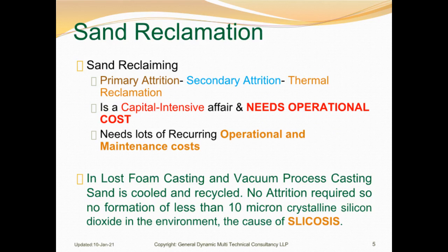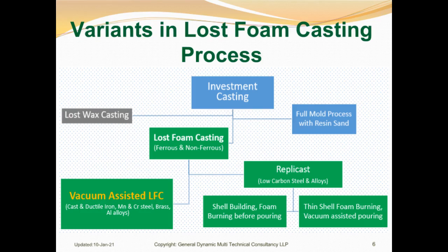Sand is a natural resource and soon going to become scarce. We already are aware of the sand mafia activities in various regions. Lost foam casting is essentially an investment casting process, where in place of wax we use expanded polystyrene, EPS, or STMMA, which is a copolymer of EPS and PMMA, that is styrene methyl methacrylate copolymer. Full mold process, Replicast, or VLFC are all essentially lost foam casting processes, but the process and practice differs in the back area or the mold closing area.